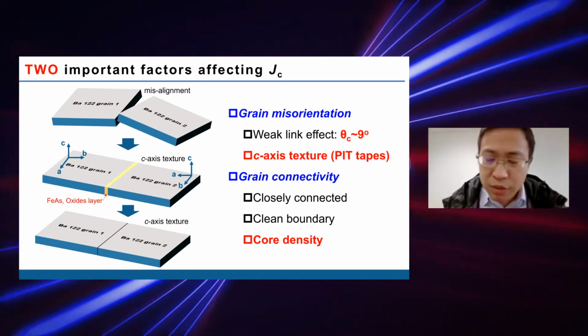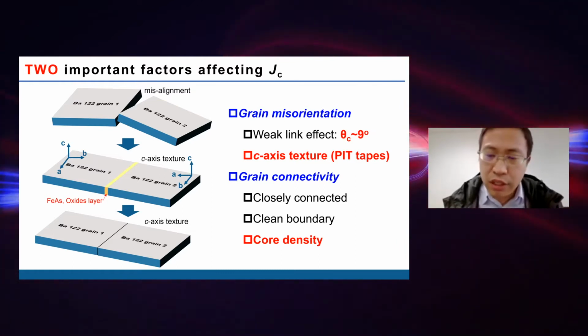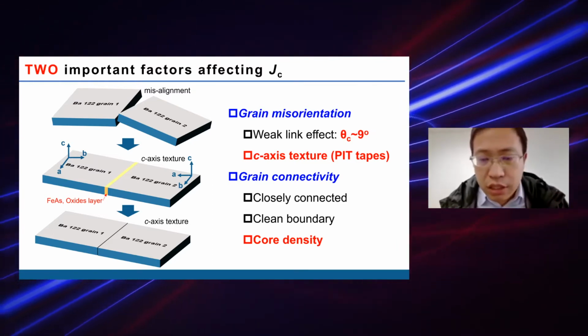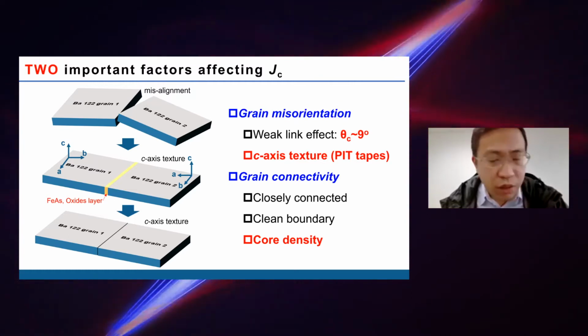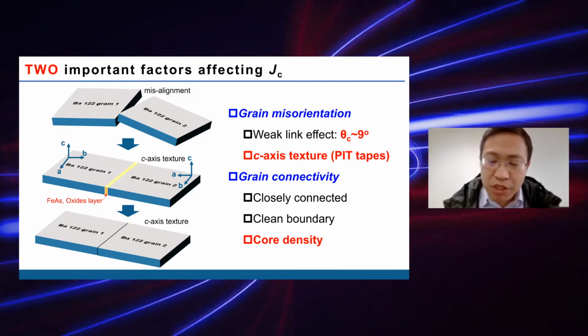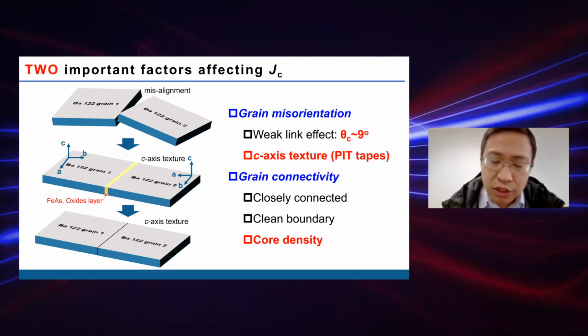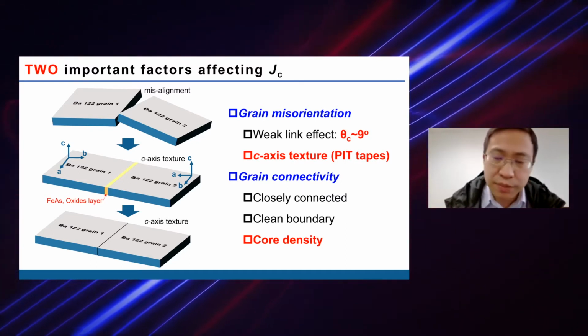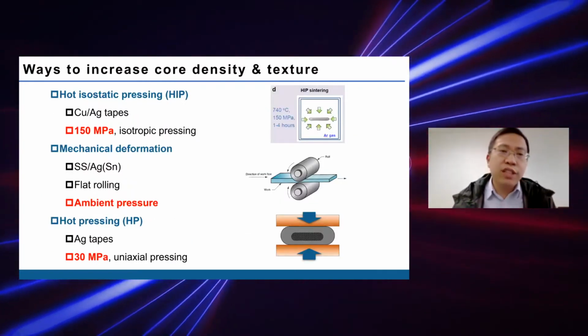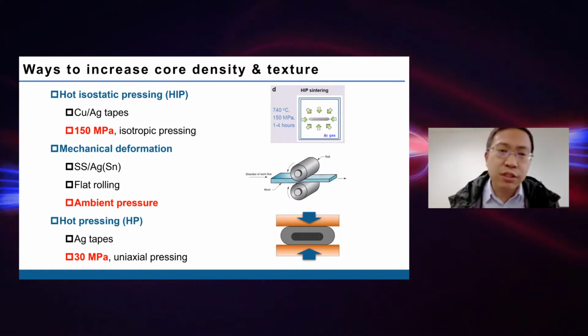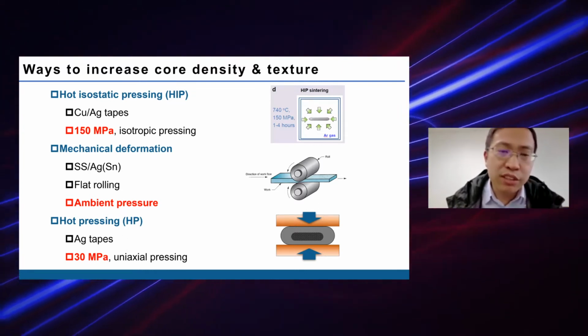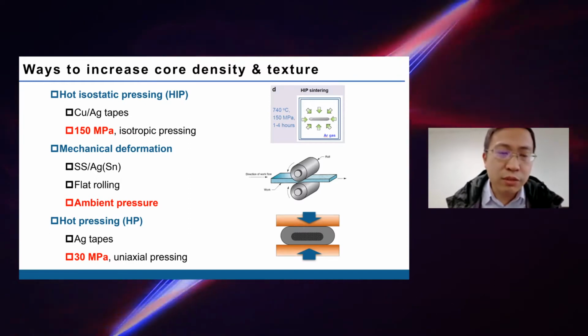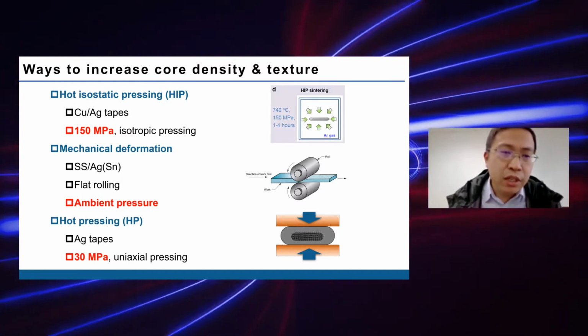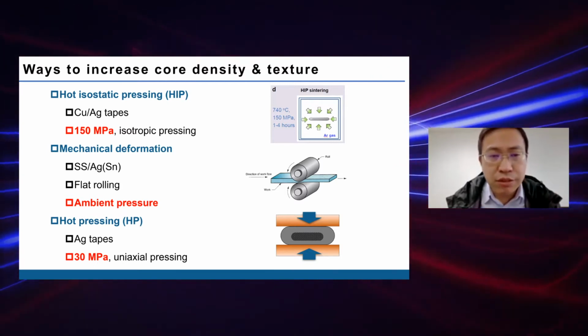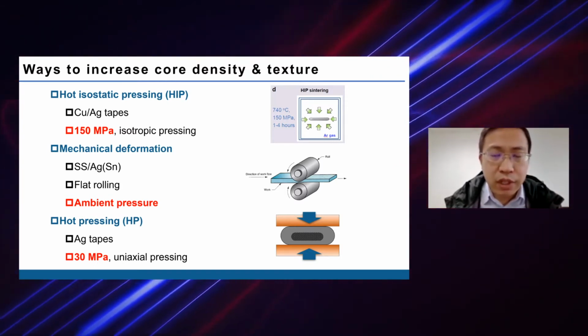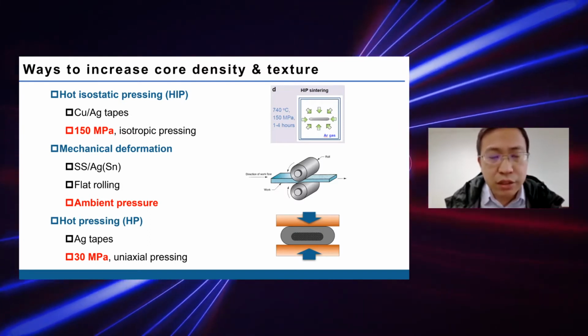The second factor is grain connectivity. The best circumstance is very closely connected grains with very clean grain boundaries. And to describe the grain connectivity, we use the core density. For now, there are 3 ways to increase the core density and texture. The first one is hot isostatic pressing. For example, we use a copper-silver architecture, and by using 150 megapascal pressure, we can achieve a very high core density. The second one is mechanical deformation,